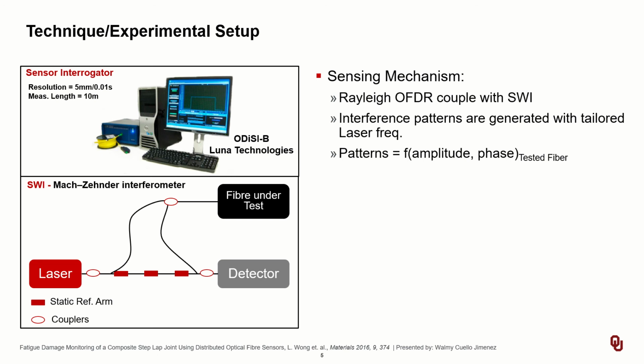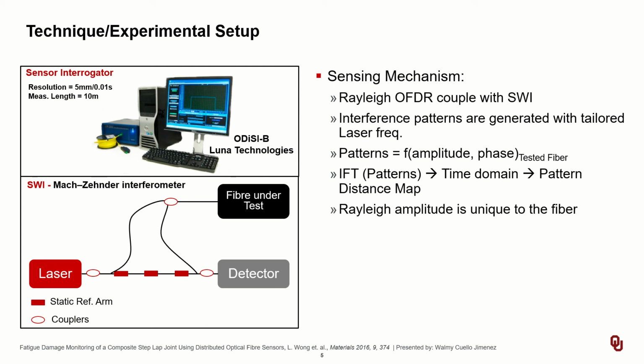Now in this work, the interference patterns are generated as frequency is tuned. These patterns are a function of amplitude and phase of the tested fiber. By employing an inverse Fourier transform of these patterns into the time domain, it is possible to construct a map of this pattern as a function of distance.